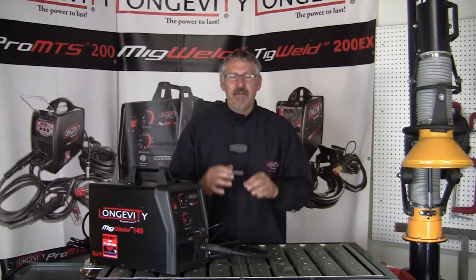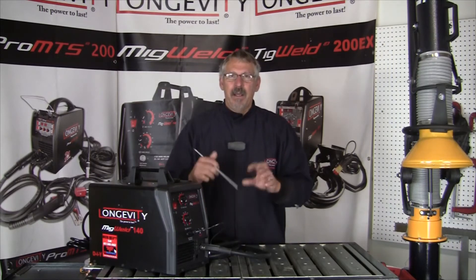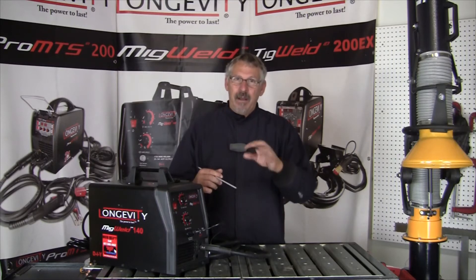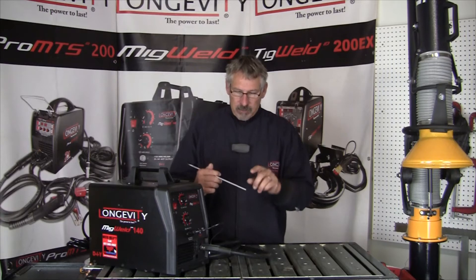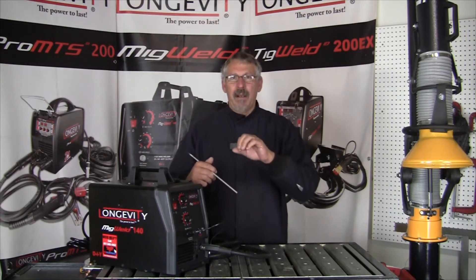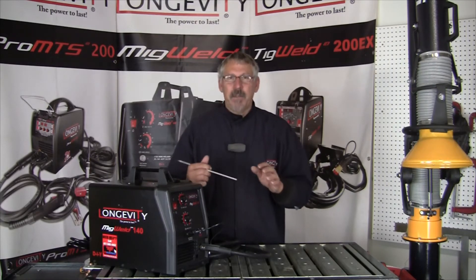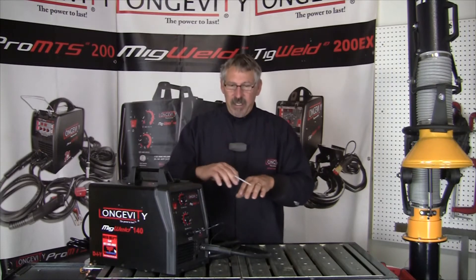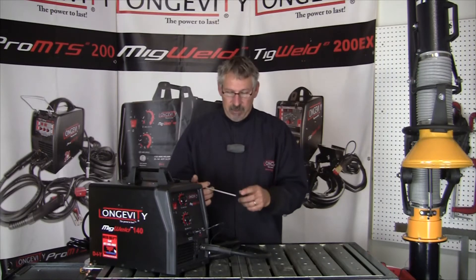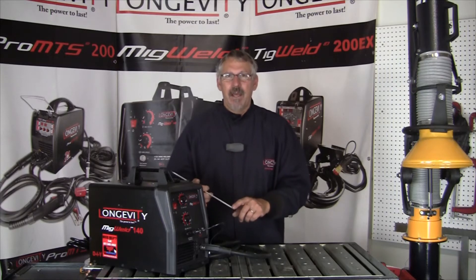The shielded gas and cellulose powder or iron powder coating the stick welding electrode is there to protect the molten steel as you're welding, but it can also get trapped. If you trap hydrogen, oxygen, or a bit of cellulose or iron powder in the weld, then that little spot is either a void of hydrogen or oxygen, or it's a little piece of slag trapped in there. You look at it on an x-ray and it's a little black spot — a defect with no strength in that little spot.